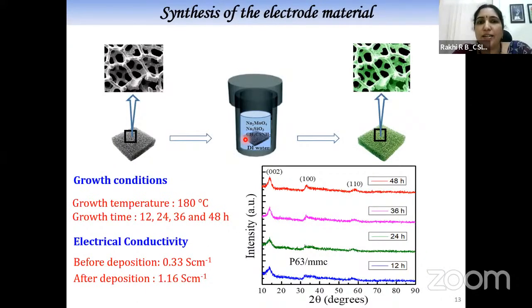So we didn't want to leave the topic, and we started preparing it in other ways. From our previous experiences, we found that there are different ways. There is the bottom-up approach, with which we will get a functionalized MoS2 sample. And the second one is another option called direct growth. Then we can avoid the ancillary binders, which give a negative, resistive effect. So we wanted to remove all those things, and we wanted to perform the direct growth of MoS2 nanostructures over nickel foam.